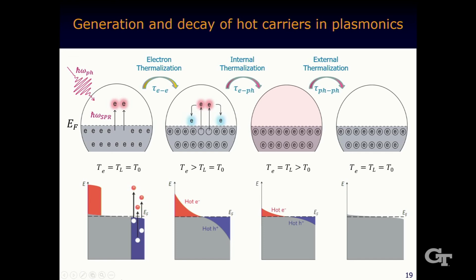At the very beginning, photons are absorbed, so some electrons gain this energy of h nu, the photon energy, and then they can reach the energy from the Fermi level, that's the initial maximum level of electron energy, to Fermi level EF plus photon energy. So this happens very fast through the process of so-called Landau damping within 100 femtoseconds. So in this case, you have energetic electrons.